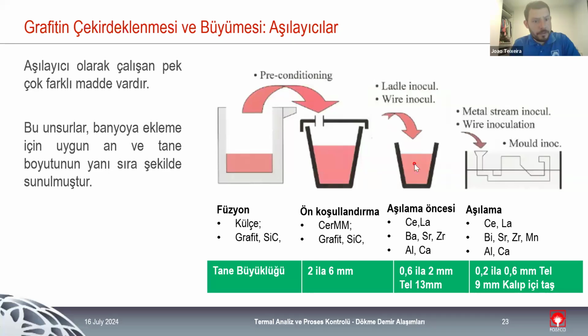We can do wire inoculation. It's a type of ladle inoculation. The only difference is that the inoculant is wrapped in a thin steel. And we have late inoculation, which could be metal stream inoculation with MSI, that we are going to see further on, or in-mold inoculation.